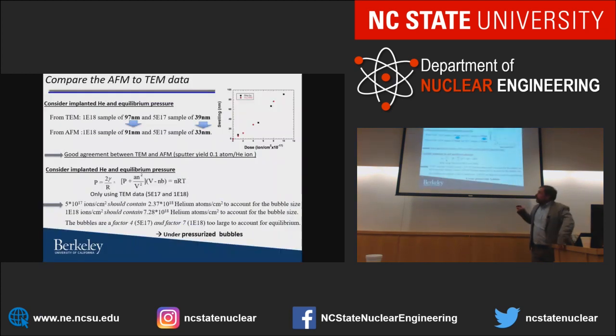And when we compare the TEM samples to the AFM samples, by TEM, by the image, we should see 97 nanometer swelling. The AFM tells us 91 nanometers. This dose tells us the TEM 39, and the AFM says 33. Pretty good match. Means we don't lose much to sputtering or some other artifact. And so we can plot swelling as a function of dose on different materials within a few hours worth of work.